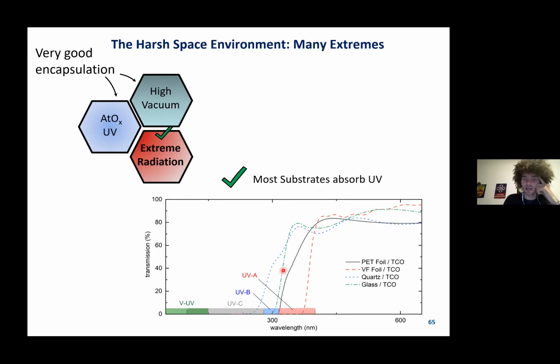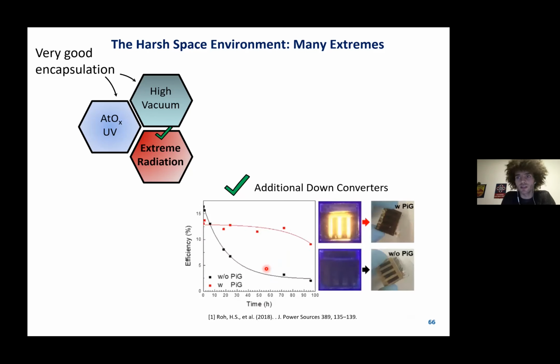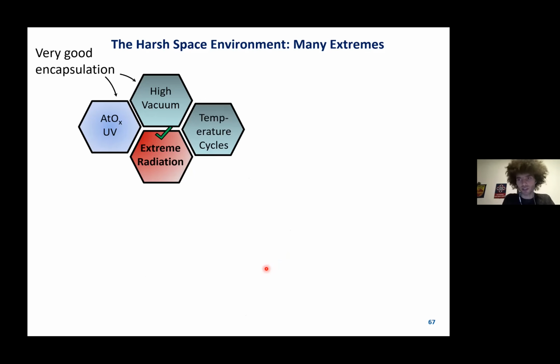Luckily, most substrate materials block harsh UV light in space. Here are just some examples. But then you could go one step further and use additional down converters to avoid UV light and by that protect the perovskite. So this would be one additional challenge. The other one is extreme temperature cycles. Imagine you're in orbit, you are facing the sun completely, so you're at around 80 degrees, but then in eclipse, in shadow, the temperature will drop rapidly to below 200 Kelvin. So this is something we don't have on Earth, but it can affect perovskites, especially because they undergo phase transitions.